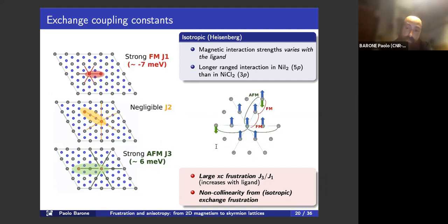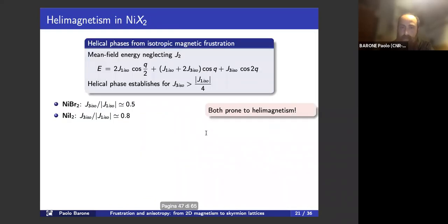And from here we have two things. We have a geometrically frustrated lattice, the triangular lattice, and a very strong competition between antiferromagnetic and ferromagnetic interactions. So one would expect a non-collinear solution for this system. This can be immediately seen by considering the mean field energy for this lattice with these interactions. And in fact, what we would expect from this mean field analysis is that there is a threshold value for the third nearest neighbor antiferromagnetic interaction, which is absolutely well fulfilled both in the bromine and in the iodine case.